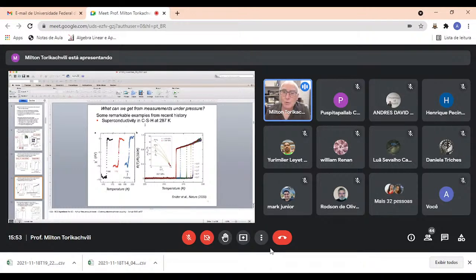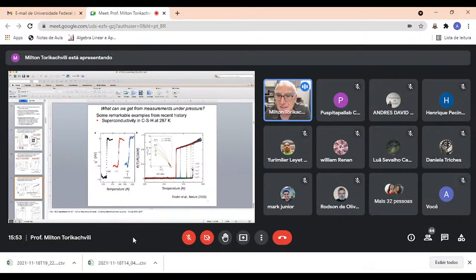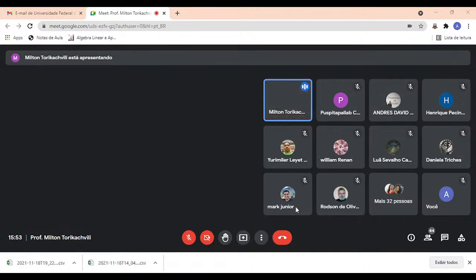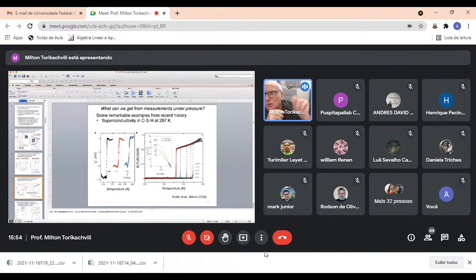So what you have here in this picture on the right is the resistance versus temperature. You see that in a field of 0 Tesla, here's the superconducting transition. I don't know where they pick up the 287. It's probably right at the middle of the transition of the resistance from the normal state to the zero resistance state. Here it's normalized by the resistance at 290, so that's why over here you're reading 1. Of course, the sample is so small, these experiments are so technically difficult. There's always the suspicion: how do you know that it's not only a very small amount of the sample that has zero resistance?